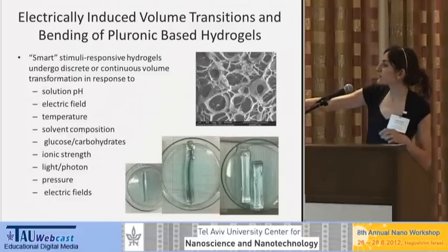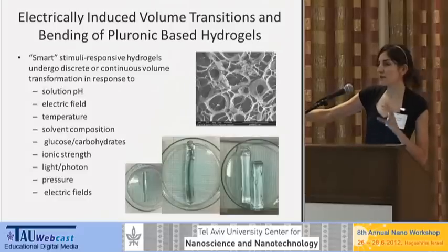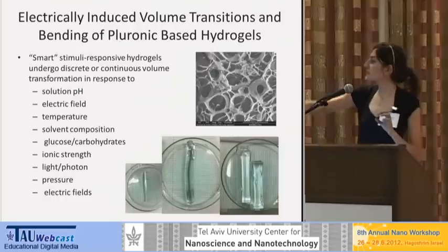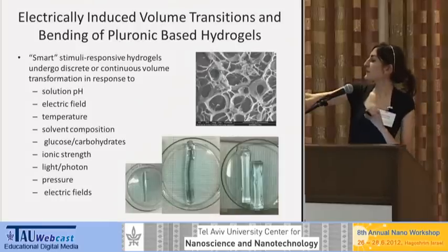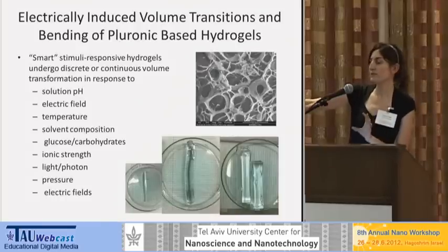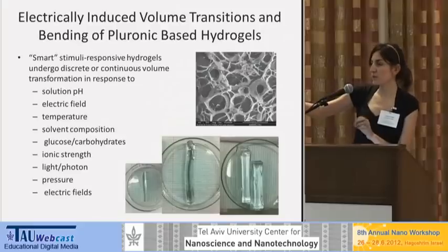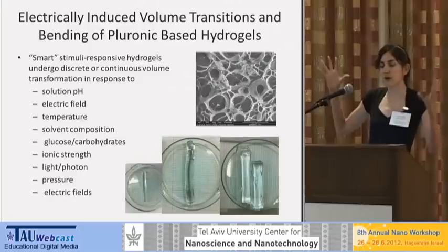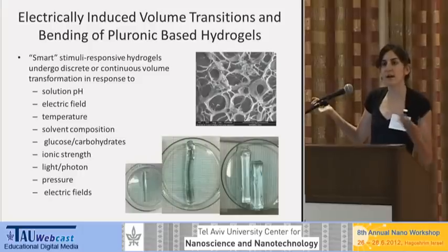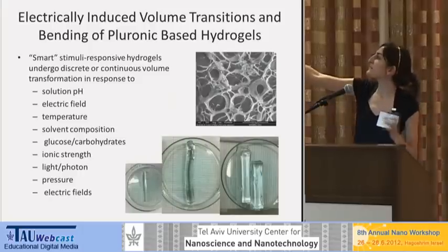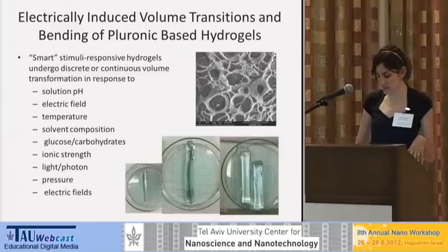And here, just to get a sense of the changes in volume that these hydrogels can undergo, over there to the left is a hydrogel that came out of a tube. That's how it was synthesized. One morning I came into the lab after placing it in water, and it had actually escaped from the beaker. It just swelled right out of it. You can get thousands of percentages of swelling. And this is in SEM, you can see the porous nature that allows for the swelling.